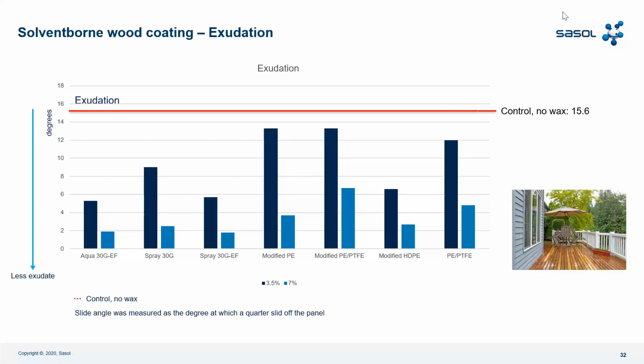So for the exudation test, the lower value is the best. Exudation is an important topic in wood coating, and you can see here that Aqua 30 GEF achieved the best results compared to the other Sasol waxes, but also achieved the best result compared to the competition, and to the control, that is without wax, which was 15.6. We achieved below 6, which is a great value compared with the competition. And it is even lower if we increase the content of wax. So with 7% of wax in polymer, we achieve below 2.